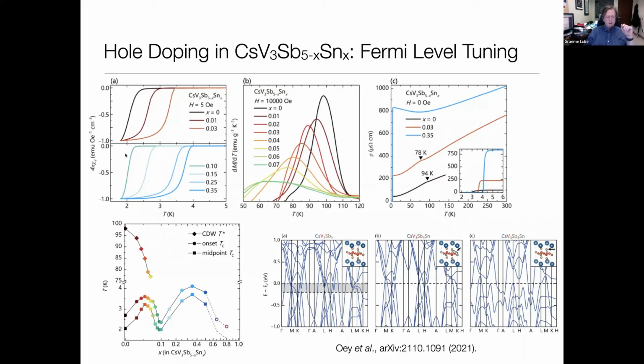And then as you further dope it up, you go through a dome, a maximum in TC, then you go down to a minimum, and then a second dome appears. Somewhat reminiscent of the picture I showed you of the triple layer graphene as well, where you had an emergent superconductivity which appeared, then went away, and then appeared again. Here it's as a function of doping rather than as a function of applied magnetic field. But the second thing you see is this charge density wave that was seen very clearly in, for example, the susceptibility. Here we're plotting the derivative of the susceptibility with respect to temperature. That CDW temperature drops dramatically, and by the time you get over here, you have no CDW anymore that's discernible.